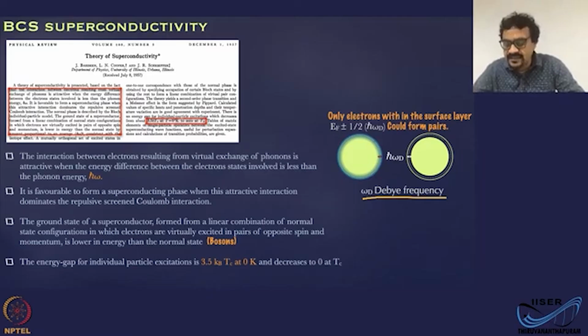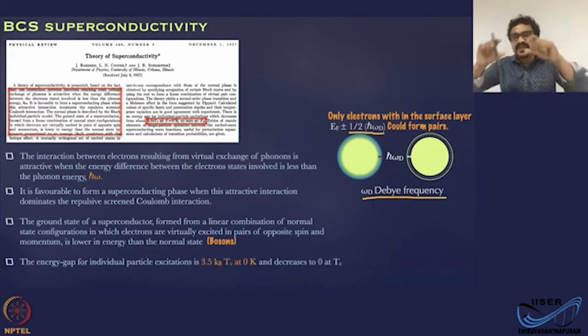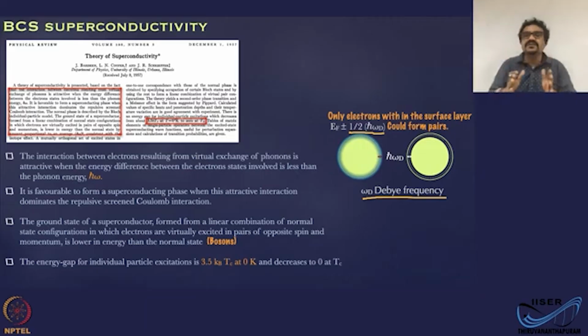So the states near the Fermi energy, on either side of the Fermi energy, which are covered by half h bar omega D, in that window will combine and condense onto the Fermi energy EF. So half h bar omega D on either side of the Fermi energy, which are covered by the Debye energy or Debye frequency, all those electrons will combine and condense onto the ground state, which is right at the Fermi energy.